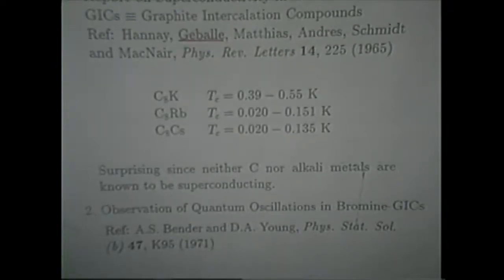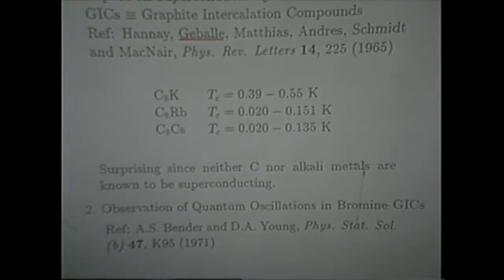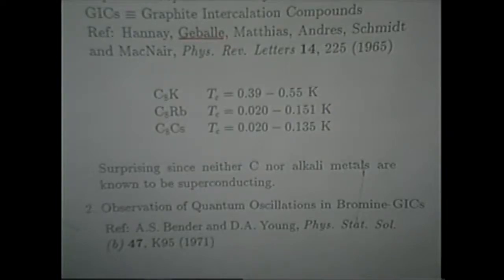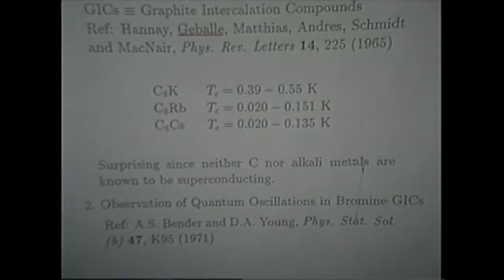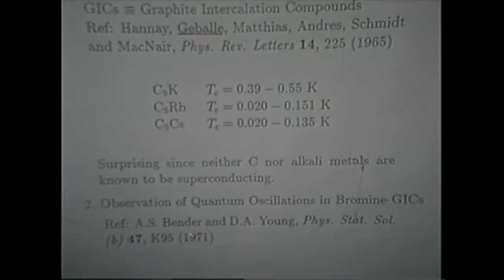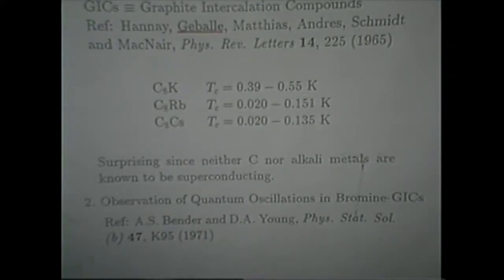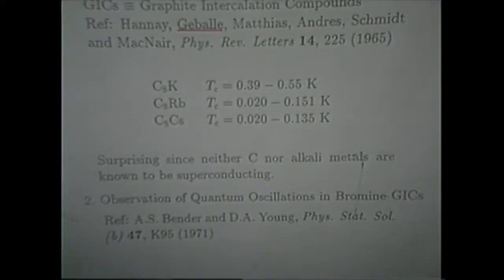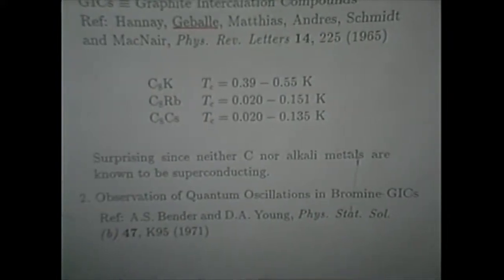Well, the boundary conditions for doing those experiments were very unfavorable at that time, and we thought about this experiment for a few years, but nothing much happened in the way of implementation until a paper was published in 1971 in European Journal. It was a very, very short paper, but what it showed is that you could see quantum oscillations in intercalation compounds. Well, what Ted Jabal did for me is he alerted me to the field of intercalation compounds, and I started following the literature sort of on the back burner. We weren't really doing anything actively, but when this paper came along, I knew we should get into the business and do something serious. And it was in this way that I got into the study of new materials.